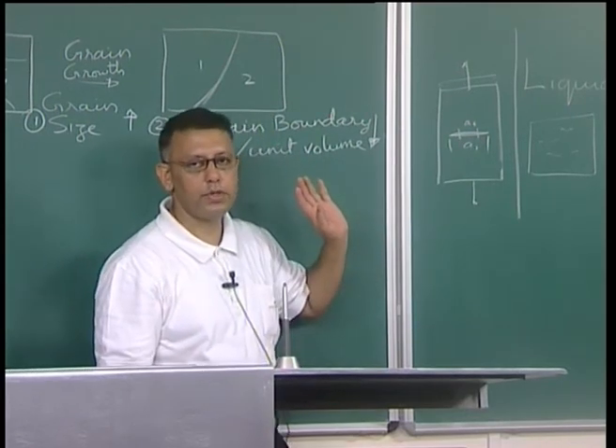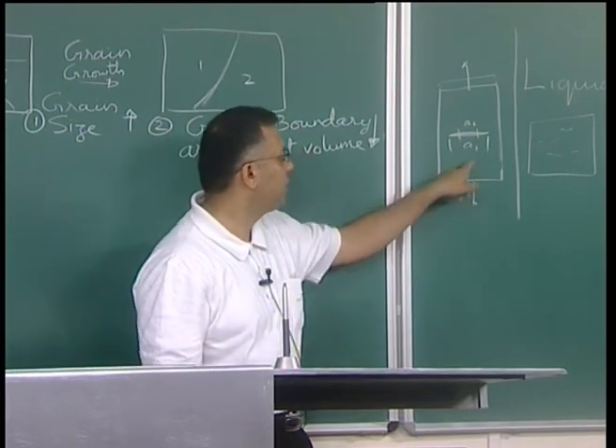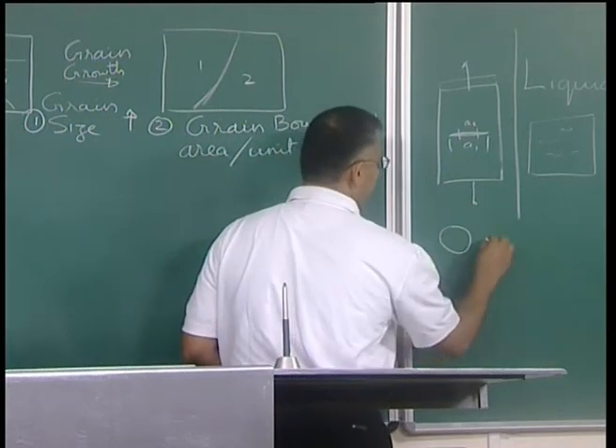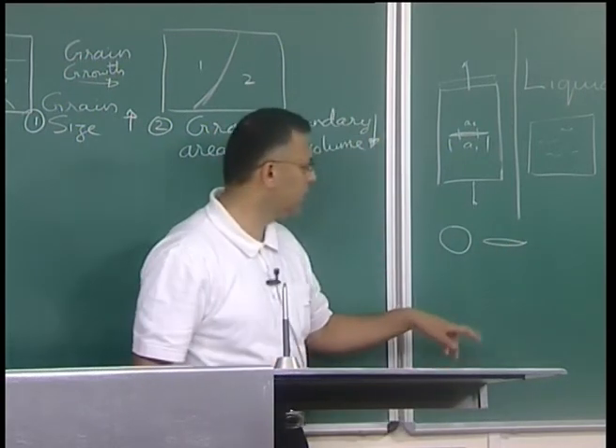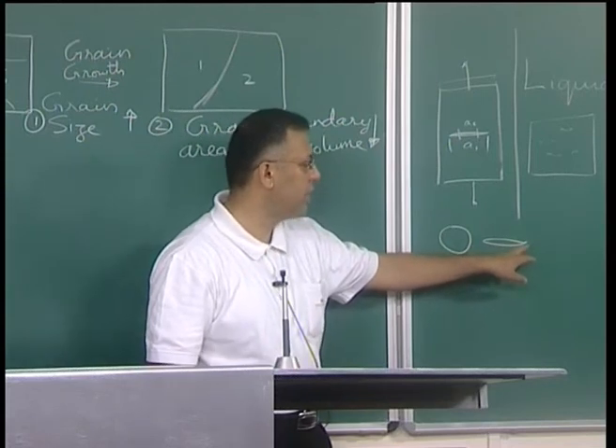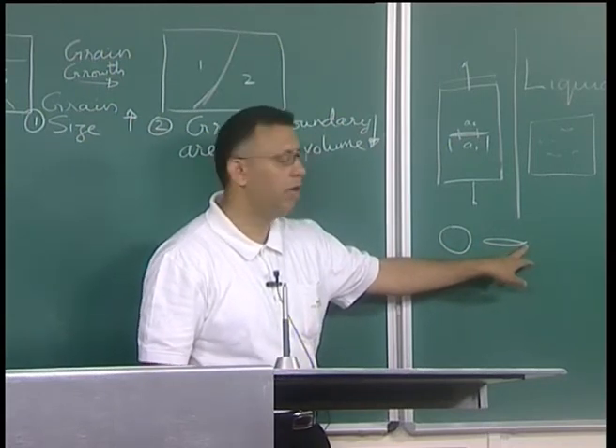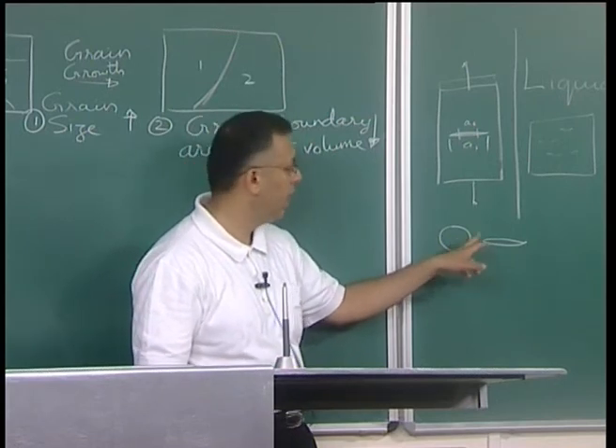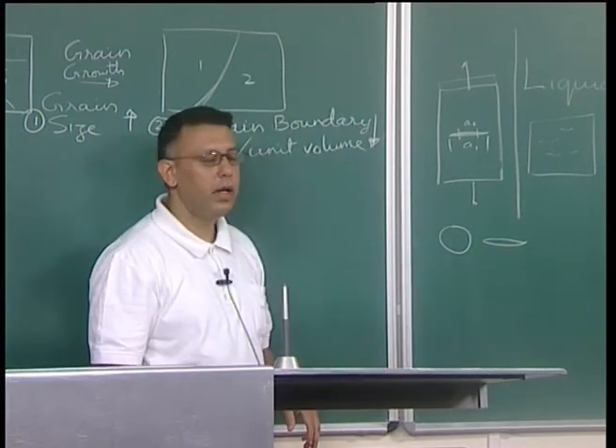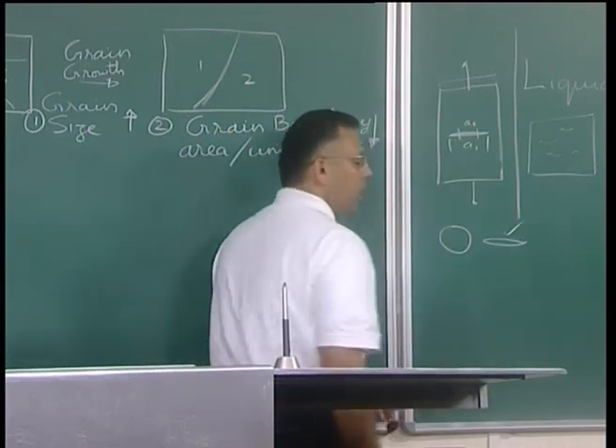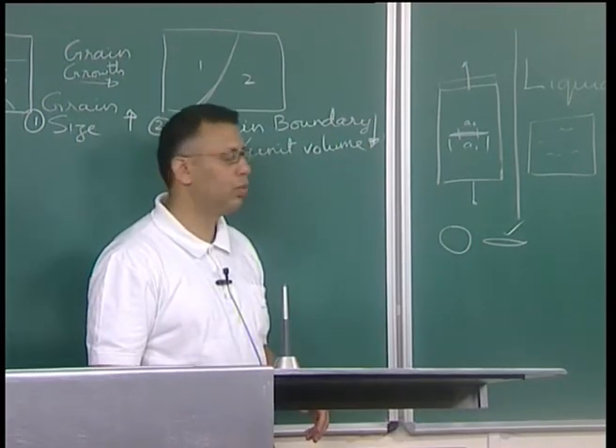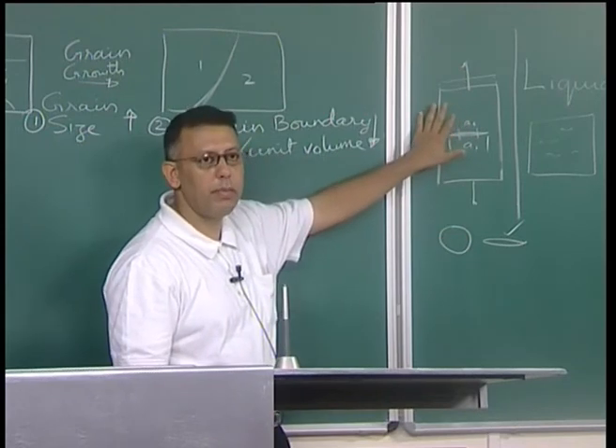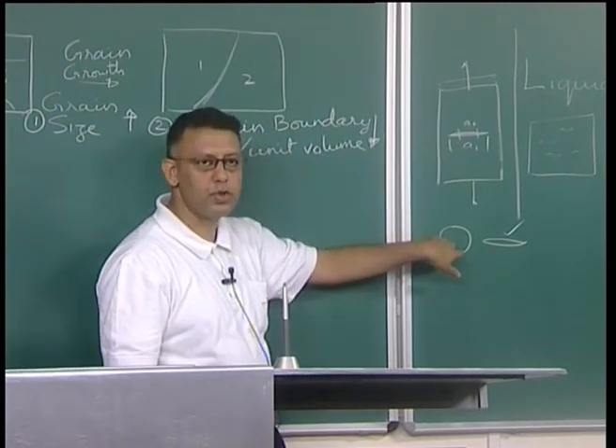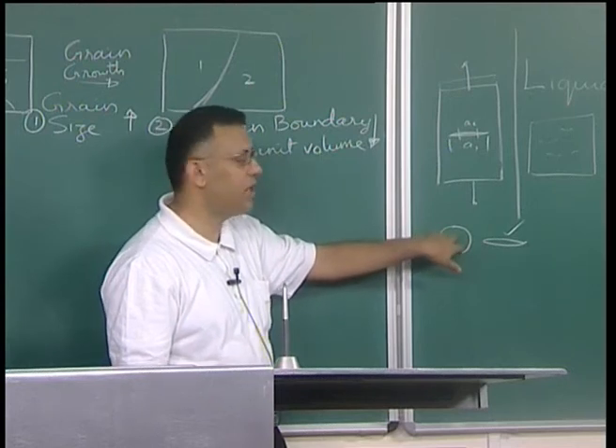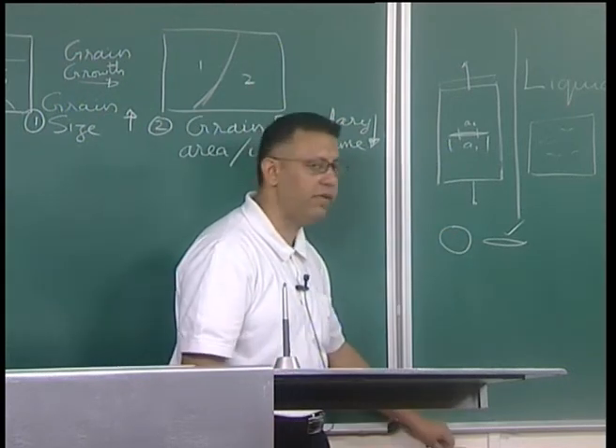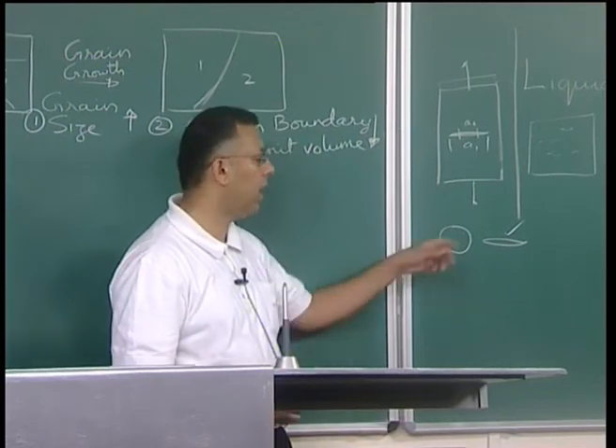But suppose for this crack growth to take place, I know that my strain energy drives this whole process. On the other hand, if I take a circular crack vis-a-vis a sharp crack like this, it is clear that the stress concentration which is needed to cause breaking of bonds is lower in the case of a circular crack as compared to a sharp crack. That means here I would not expect a good chance of crack growth. Even though the overall energy stored in the body may be large here, crack growth will not take place because locally enough energy density or enough stress is not available at the tip of the crack to break the bonds.